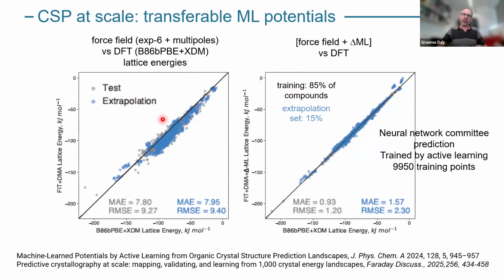And on the left, what I'm showing you is agreement between the baseline force field here and the density functional theory accurate lattice energies here for all of those structures. Okay, and you can see we have errors of around 8 or 9 kilojoules per mole. So when I showed you really good ranking results for this database, we were relying quite heavily on cancellation of error, because we have absolute errors of 8 or 9 kilojoules per mole, but it looks like we get relative energy ranking of structures quite well.